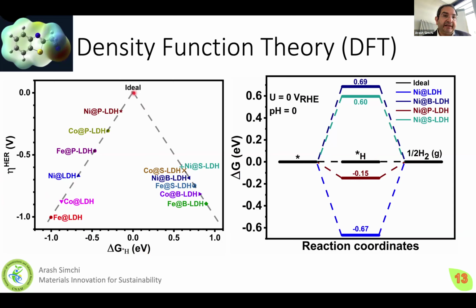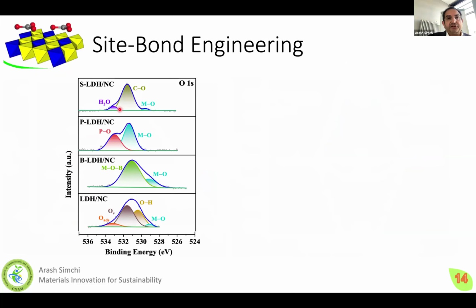And this is the ideal point, meaning that the overpotential is zero. So this diagram gives us a very good indication of which materials have to be selected without going to the laboratory and doing a lot of experiments. After knowing that, my research group started to fabricate this system. For example, as you see here, sulfur inside an LDH structure, phosphorus, boron, and so on.